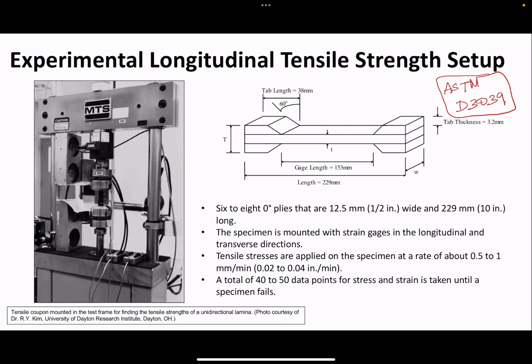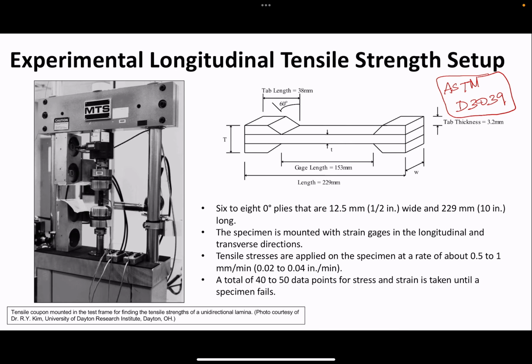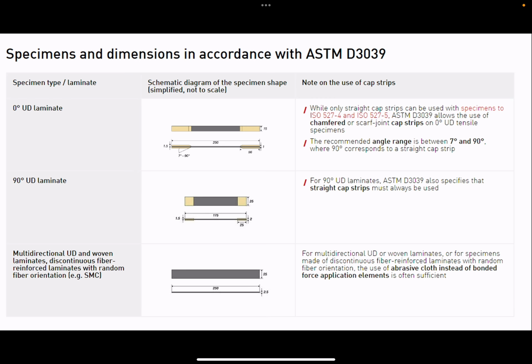The specimen is mounted with strain gauges. You've seen extensometer before, so it's similar to that. It's mounted with strain gauges in the longitudinal and transverse directions because we want to record both. Tensile stresses are applied on the specimen at a rate of about 0.5 to 1 millimeter per minute, and 40 to 50 data points are obtained. And then using those data points, we draw graphs.